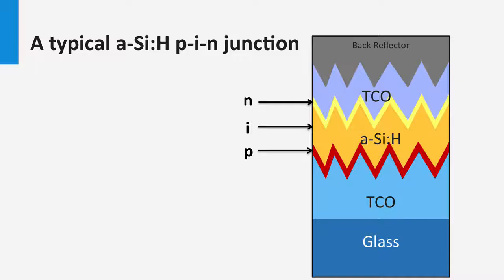Typical TCO layers are fluor-doped tin oxide, aluminum-doped zinc oxide, boron-doped zinc oxide, hydrogen-doped indium oxide, ITO, which is tin-doped indium oxide. These films are processed using either sputtering, low-pressure chemical vapor deposition, metal organic chemical vapor deposition, and atmospheric pressure chemical vapor deposition.